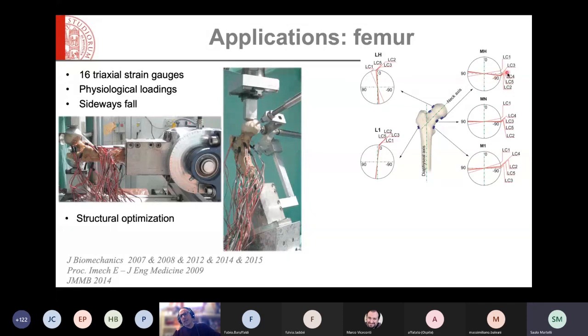These plots show the alignment of the principal strain when we tilted the femur at different angles. So we found that the femur is optimized to have the principal directions always at a very narrow angle with respect to the femur. So this allows the principal strains to be aligned with the main directions of strength of the tissue, and it is very robust to different loading directions. And this is not the case when you happen to hit on a side and have completely different loading.